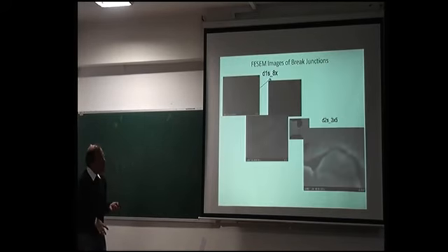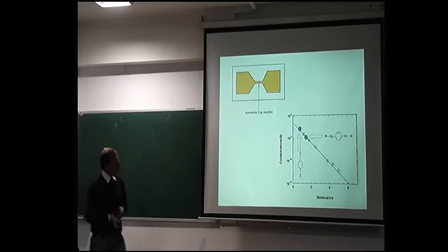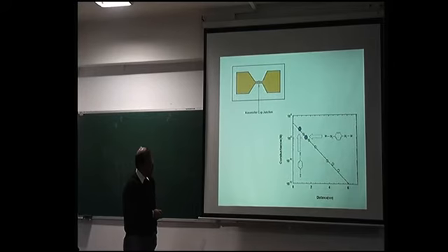Okay, so you can go down. This is another FESEM picture. You can make out from here that this gap is less than 5 nanometer. It's not very easy to make a lithography-defined 5 nanometer or even 4 nanometer gap, but by this method you can create it very easily. Even people have created, I know one group in Cornell, almost close to 1.5 nanometer by this technique.